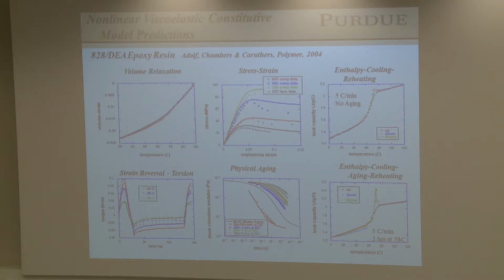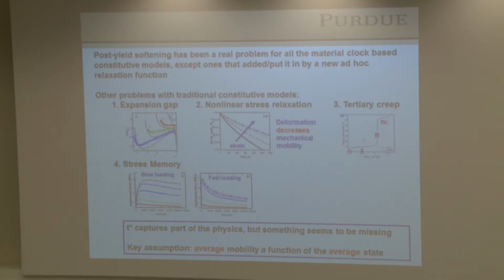Now, probably I would have been wise to stop at that point and say, job done, and I quit. But we noticed that we're not doing a really good job right here. In other words, we predict the overshoot, but this post-yield behavior we really couldn't get. For a while we tried to ignore it, and for a while we tried to work and see how we could make things happen. Then we started to ask, are there other things that are wrong? It turns out when you look at the data completely, there were a whole bunch of other things that were wrong. So this t star idea captures part of the physics, but something is missing. We worked many years trying to figure out how to get that to work. At some point, we finally sat back and said there's something more fundamentally wrong with this whole group of models that are out there.